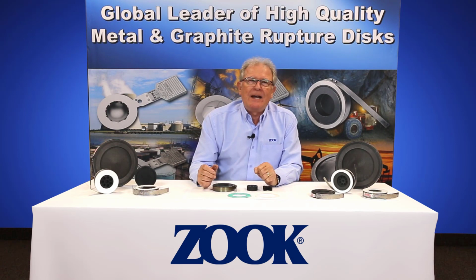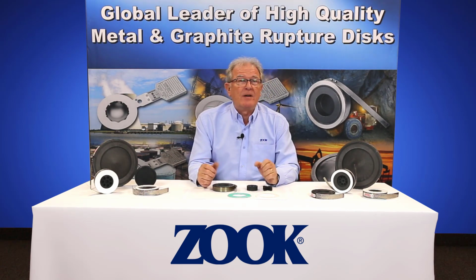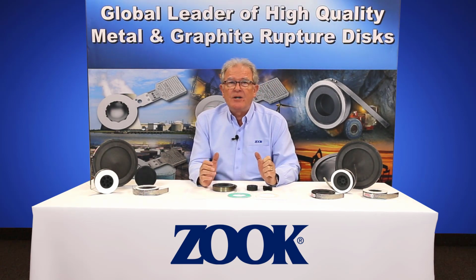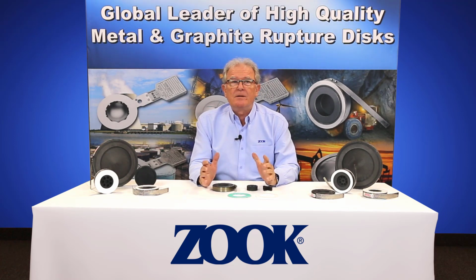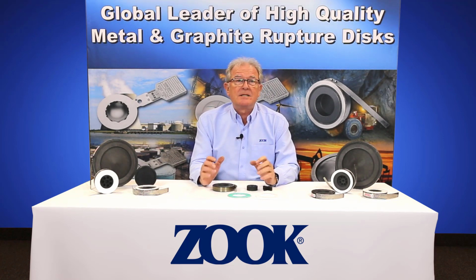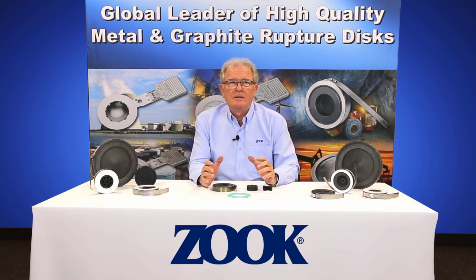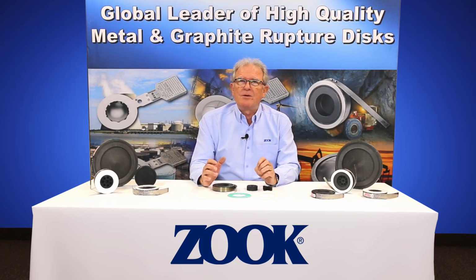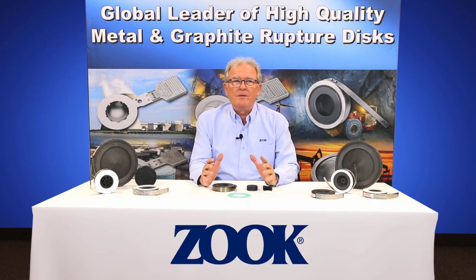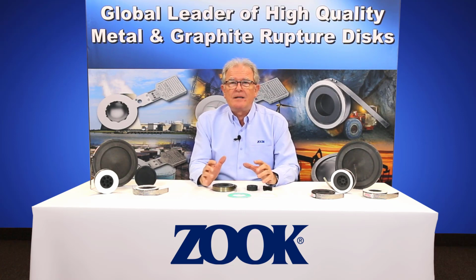ZOOK implements an impregnation process with phenolic resin, which is a proprietary operation that includes multiple vacuum, pressure, and special thermal curing cycles. Once the impregnation process is complete, then the impervious graphite material is machined to produce the finished graphite disc that has been ordered by the client.